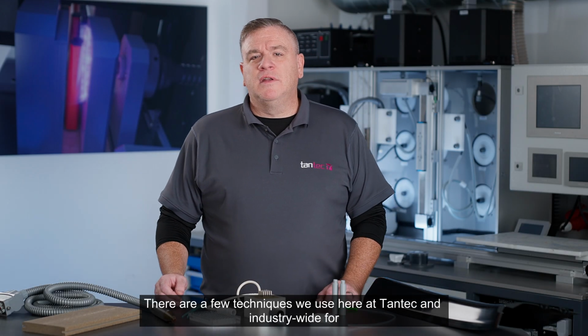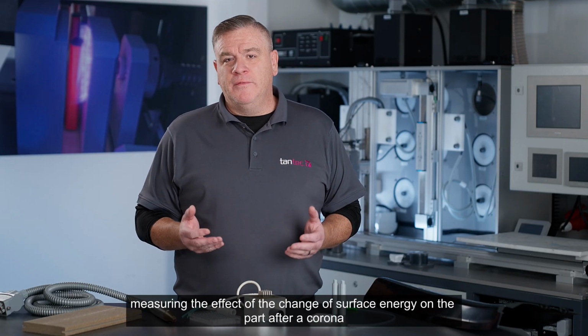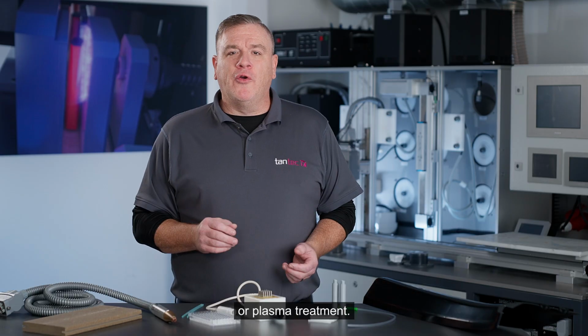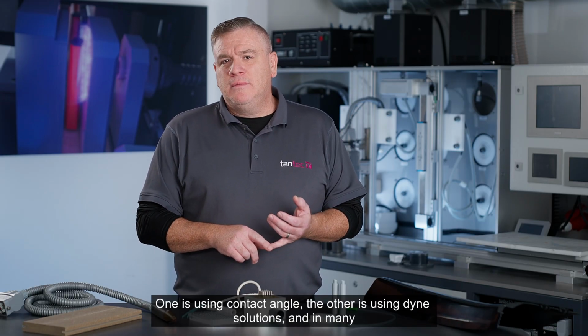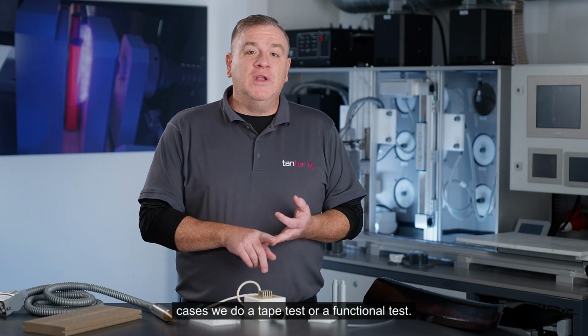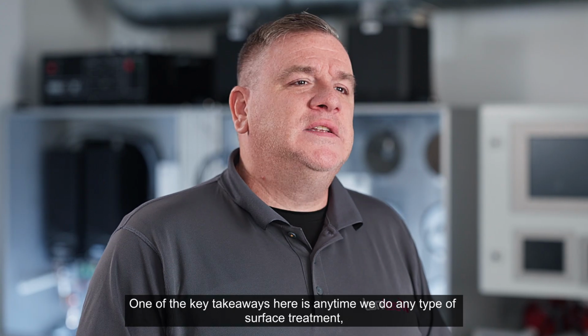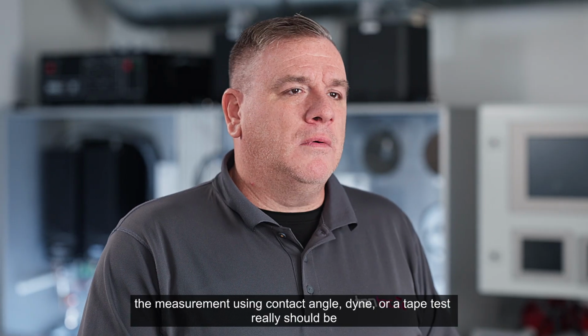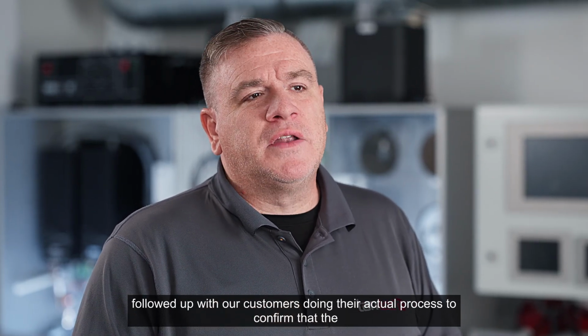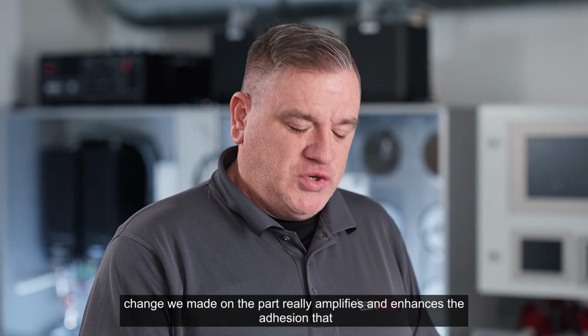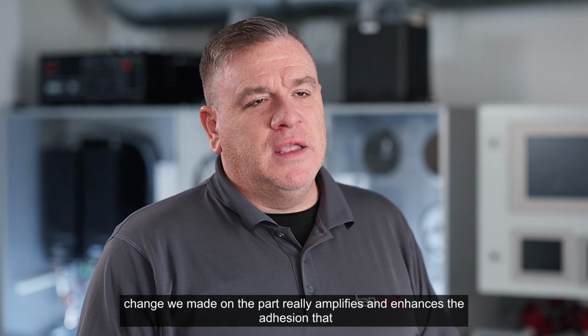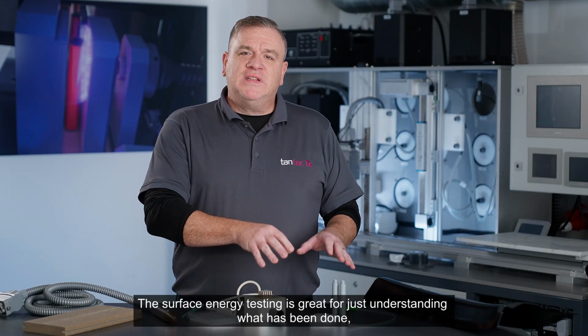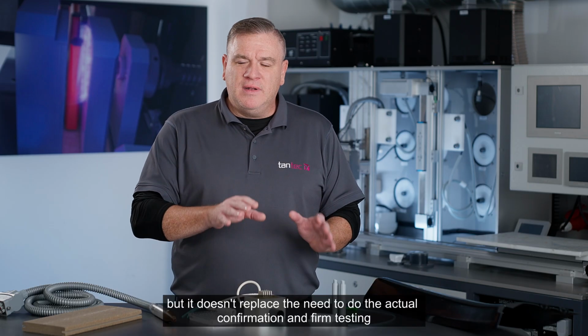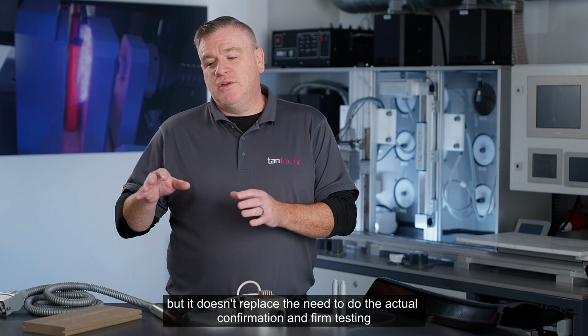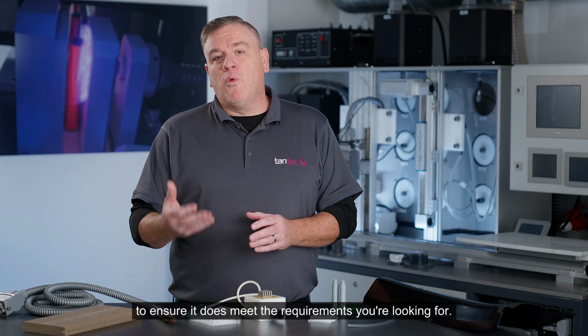There are a few techniques we use here at Tantec and industry-wide for measuring the effect of the change of surface energy on the part after a corona or plasma treatment. One is using contact angle, the other is using dyne solutions, and in many cases we do a tape test or a functional test. One of the key takeaways here is anytime we do any type of surface treatment, the measurement using contact angle, dyne, or a tape test really should be followed up with our customers doing their actual process to confirm that the change we made on the part really amplifies and enhances the adhesion that they're looking for. The surface energy testing is great for just understanding what has been done, but it doesn't replace the need to do the actual confirmation and firm testing to ensure it does meet the requirements you're looking for.